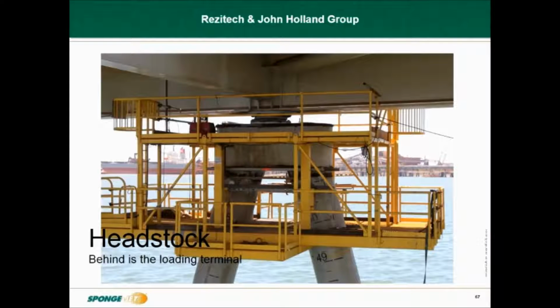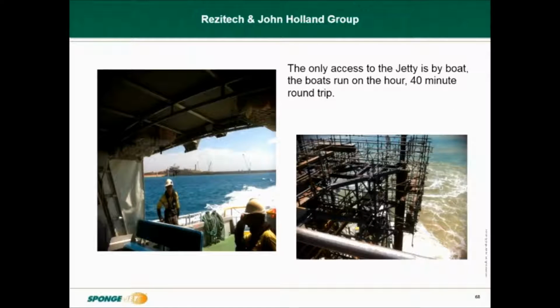We presented and showed that they had the bones of the job, the scaffolding already in place, so all they have to do is set it up for Sponge Jet and look at doing that process. We pointed out to them that they were always having problems with any abrasive blasting over water, and to get Garnet out there, the mobilisation and demob. I explained that if they were set up with Garnet, the project would have delivered 220 tonnes of media onto the project to recover it, and at the same time they had to demob the Garnet and dispose of the spent media as well. We showed them that there were savings of $180,000 by changing over to sponge blasting on the same project.